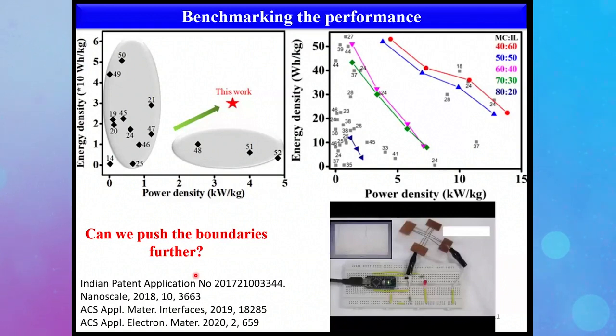Shana asked, when the CNT threads are in the polymer electrolyte, the parallel position between the two CNT electrodes is very low. For example, the interaction point between the two lines is a plus symbol. There's only a point which is very low when compared to the length of the line. Yes, so what this slide shows you is that these are junctions, but the remaining part of the thread is unused. We have just wantedly left it unused. You can create as many junctions as possible.